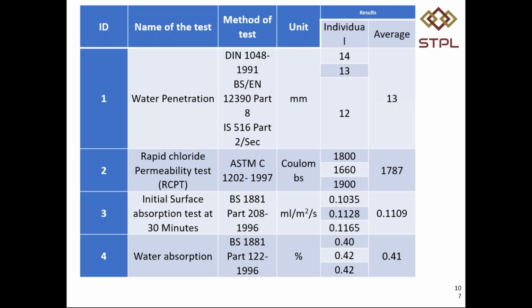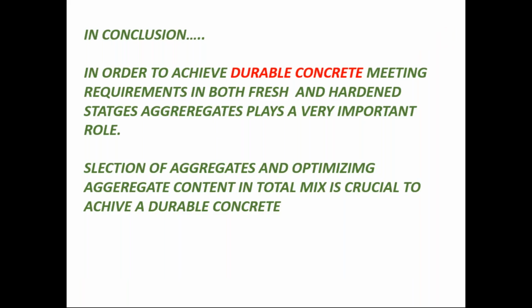These are the typical values for the water penetration test, rapid chloride permeability test, and initial surface absorption test. Water absorption is another simple test nowadays becoming more and more popular. If the concrete is very well compacted and has a good gradation of aggregates, the water absorption can be less than 1%, but normally it won't be so low. In normal concrete, it will be at least around 2% or so. But this particular concrete was a high strength, high performance concrete, maybe because of that we got such very low values. So water absorption is a very useful durability test which we do.